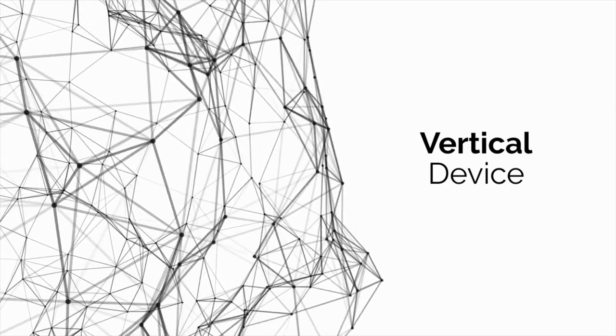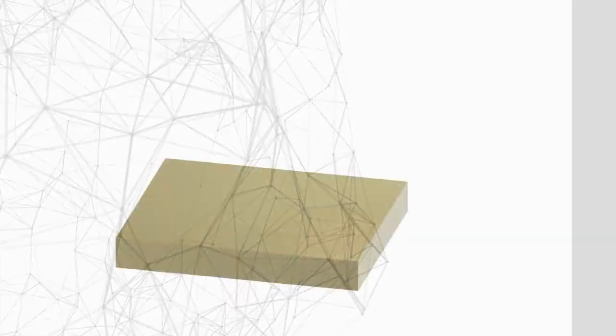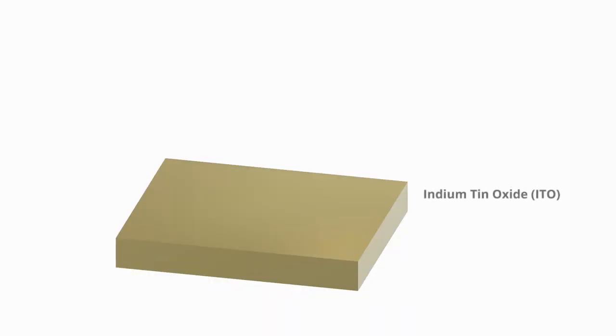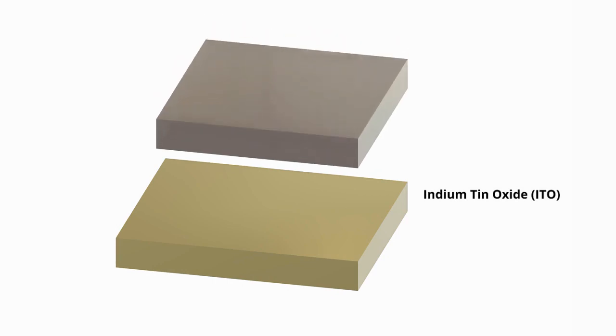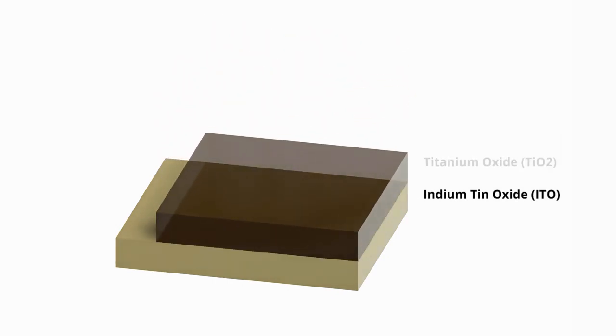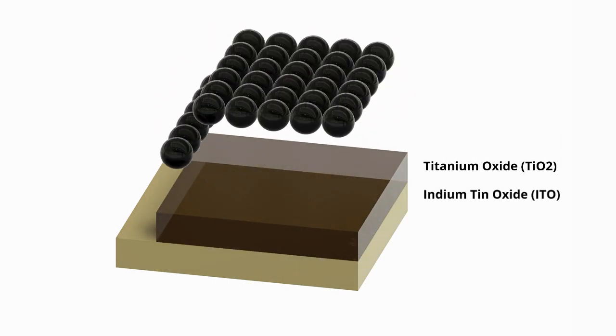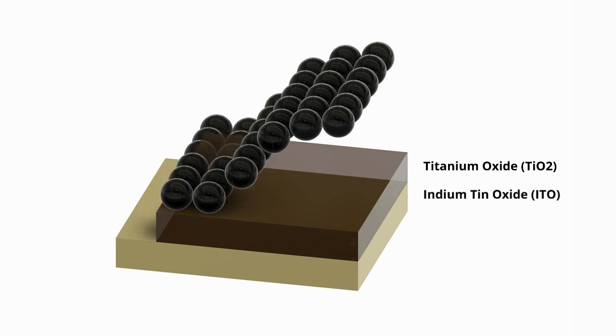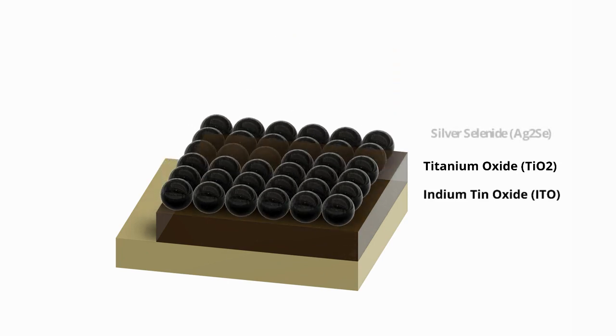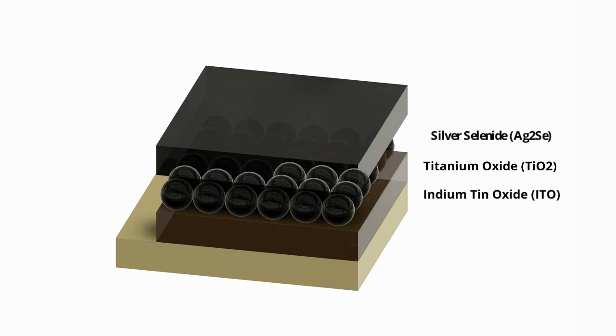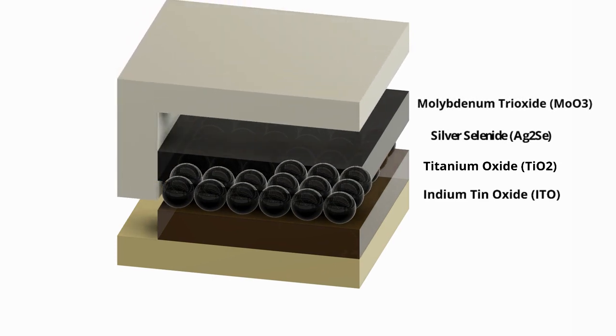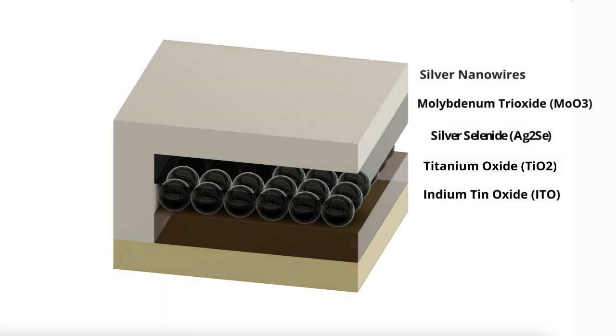With this quantum dot thin film, we made photodiodes. There are in total 5 layers in our photodiodes. From bottom to top, there are indium tin oxide, which serves as bottom contact, titanium oxide, which is the electron transport layer, silver selenide quantum dots, which is the photoactive layer, molybdenum trioxide, which is the hole transport layer, and silver nanowires, which is the top contact.